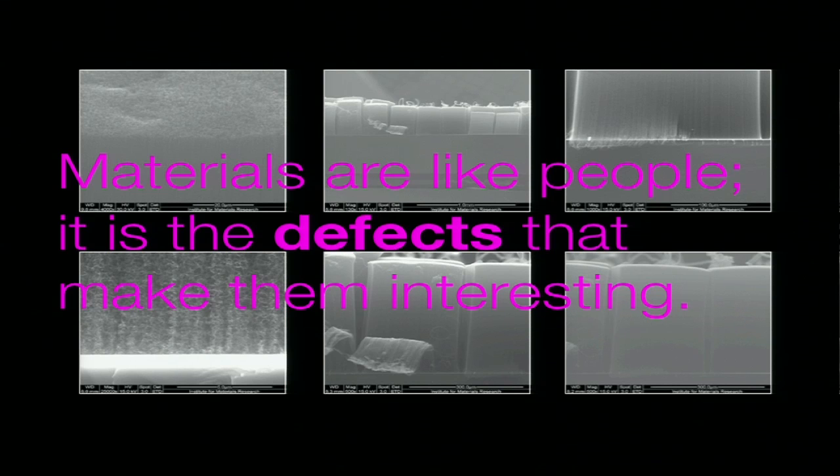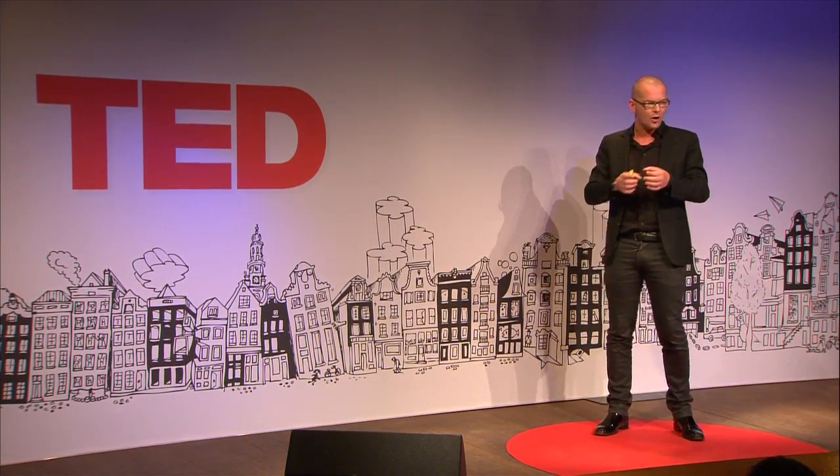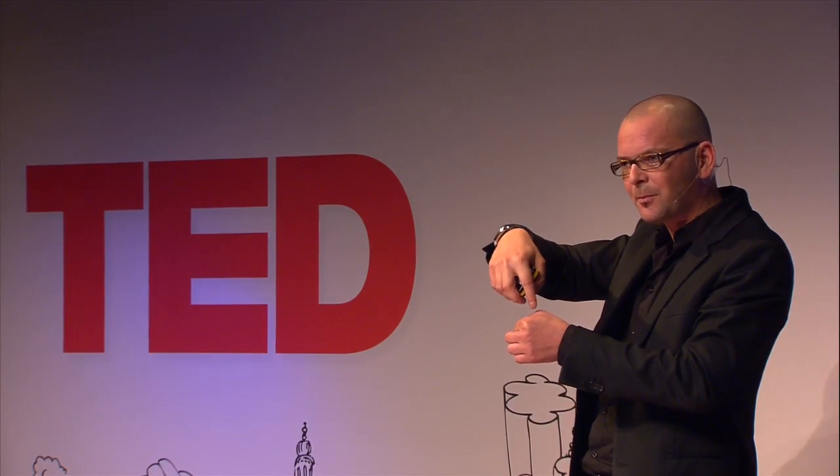There's just one thing I have to explain here. It's called the cavity principle, and that's how we capture all light. I told you about these carbon nanotubes, which have a very thin diameter. Now let's think about a ping pong ball, and this ping pong ball is a photon. You have a box which is totally empty, and you make a little hole in there. This photon travels to the box, slips into the little hole, and there it gets lost. The chance that it gets out is almost nil. That is the cavity principle. That happens also with these carbon nanotubes, because this photon cannot enter the carbon nanotube. It can only go in between the vertically aligned carbon nanotubes, where it will travel under the surface and probably never surface again.